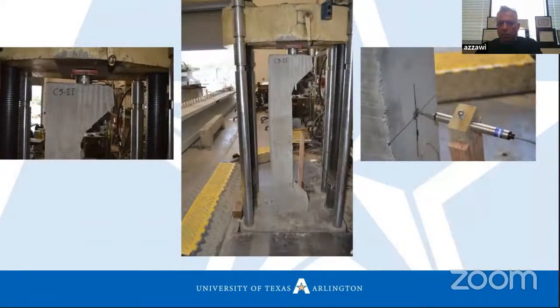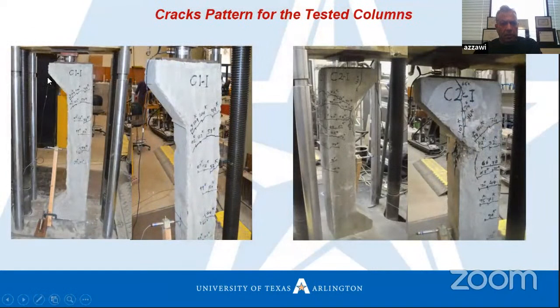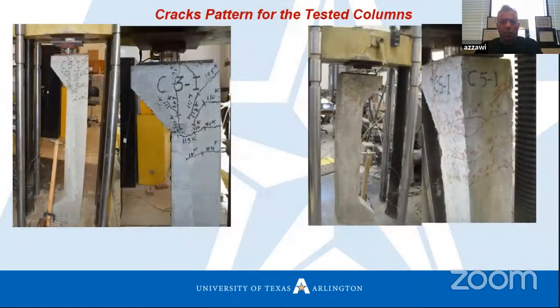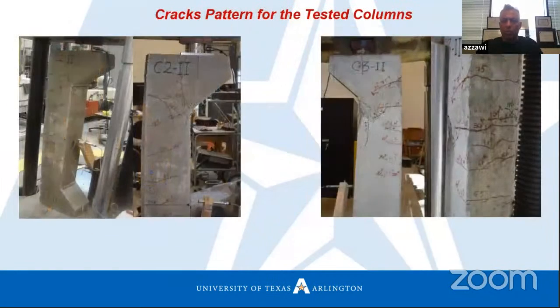So I tested all the specimens I have, and these are some results for the crack pattern of the tested columns. As we see, we have different strengths and different crack patterns. Once we increase the steel ratio, the behavior is much better and the column can resist more load. The capacity is also increased.